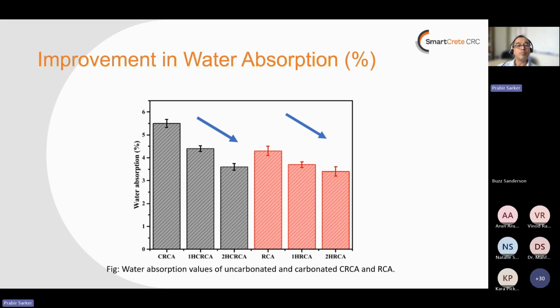And some of the physical properties, looking at the water absorption of CRCA without any carbonation, 1 hour carbonation and 2 hour carbonation. So you can see higher length of carbonation can improve the water absorption of the aggregate that is produced after carbonation. And the effect is similar in the other recycled aggregate as well.